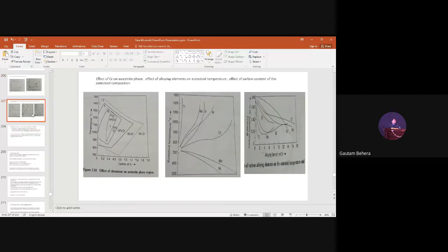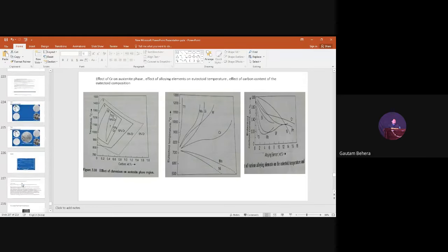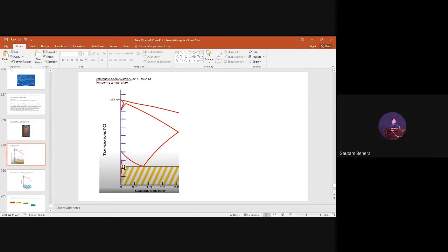He is exactly true. You can see titanium, molybdenum, silicon, tungsten, chromium, all are ferritic stabilizers. They stabilize the ferrite phase. You understand, below this temperature, the A1 temperature, lower critical temperature, ferrite is the stable phase, and above this, austenite is the stable phase, right? So if we add more ferrite stabilizer, what will happen to this eutectoid temperature? It will go up, obviously. Why? Because it wants to stabilize the ferrite phase. So the ferrite region will increase if this A1 line goes up, right?